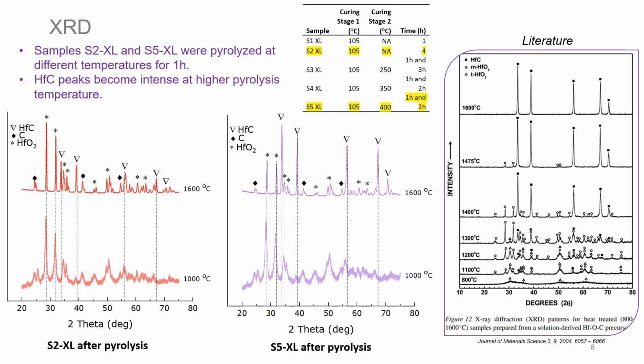To determine the formation characteristics of hafnium carbide ceramics at different temperatures, the cross-linked samples S2 and S5 were pyrolyzed at different conditions. Here, the XRD of these samples pyrolyzed at 1600 and 1000 degrees centigrade are presented. As expected, at a lower temperature of 1000 degrees C, we see mostly hafnium oxides present in the ceramics, whereas with the increasing temperature to 1600 degrees C, the hafnium carbide becomes prevalent in both cases, especially for sample S5, which was cured at a higher temperature compared to sample S2. The hafnium carbide peaks were more prominent than hafnium oxide peaks.